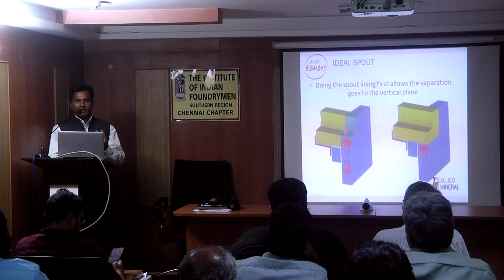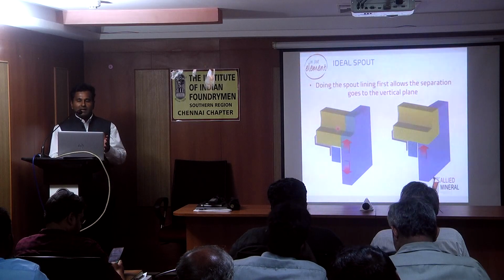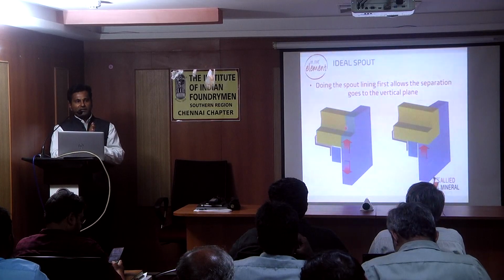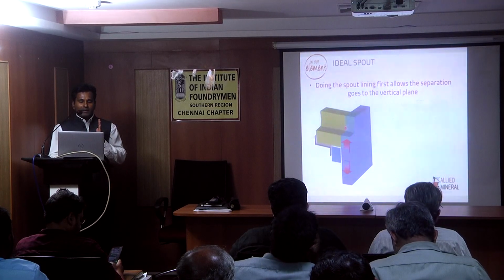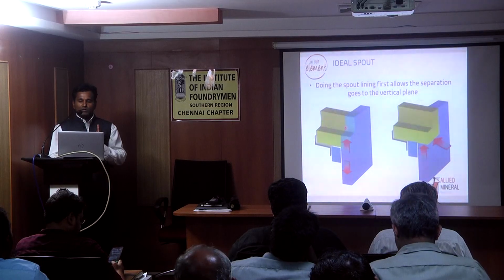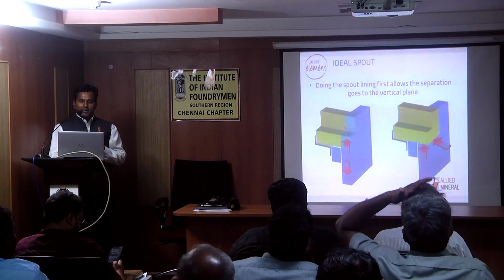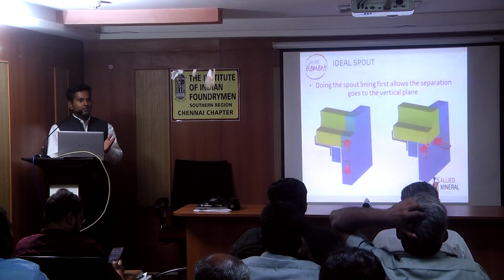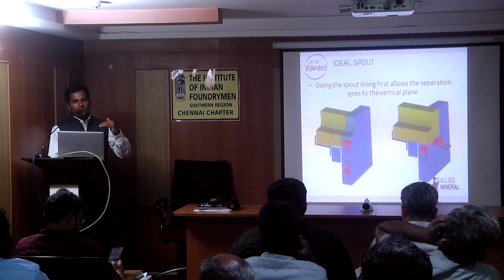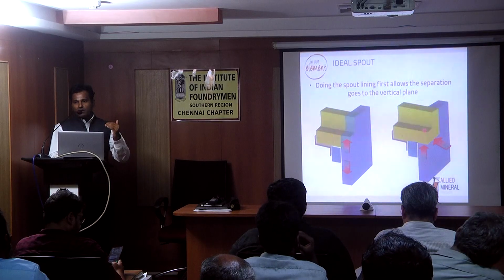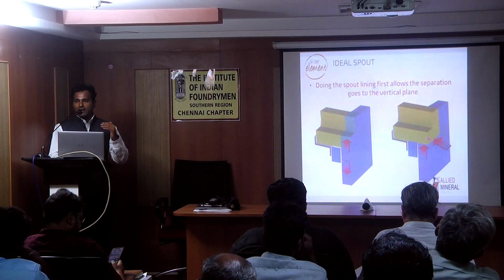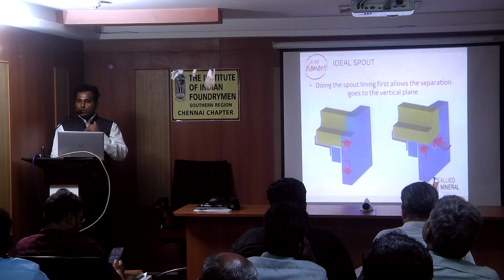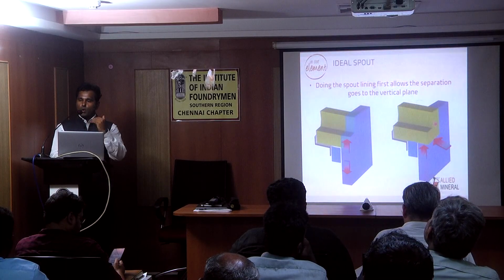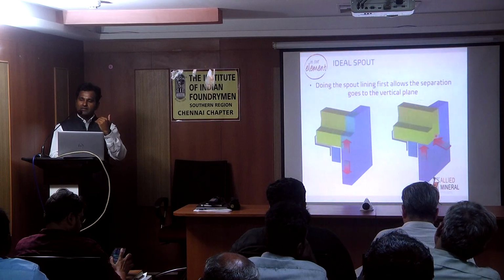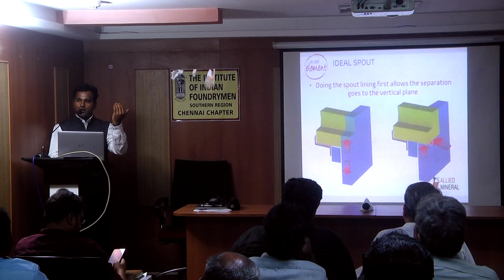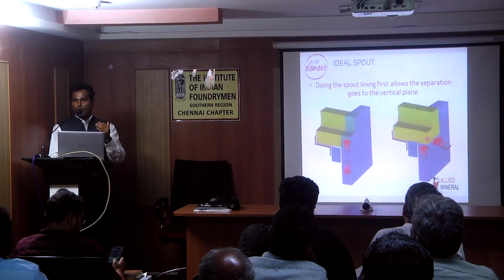We call it a vertical plane design. In the vertical plane design, these two become completely different entities, so when the lining tries to expand and contract, it will not disturb your spout. In the conventional practice, people put the spout lining on top of the main working lining. Spout refractory and the main working refractory have different expansion rates. When the main working lining tries to expand, it will push the spout lining. When it contracts, there will be a separation, and because of the expansion ratio, it doesn't seal properly.